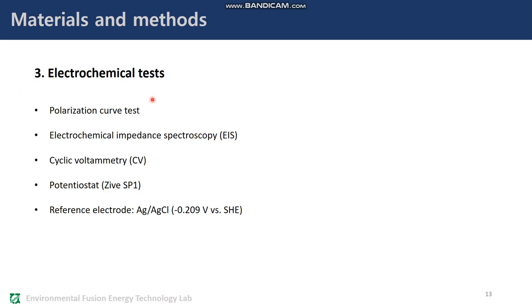Three, electrochemical tests. Measurement of polarization curves, electrochemical impedance spectroscopy analyses, and cyclic voltammetry were done with a potentiostat. For electrochemical measurement, an Ag/AgCl reference electrode was inserted in the medium and located very close to an anode to minimize anodic solution resistance.